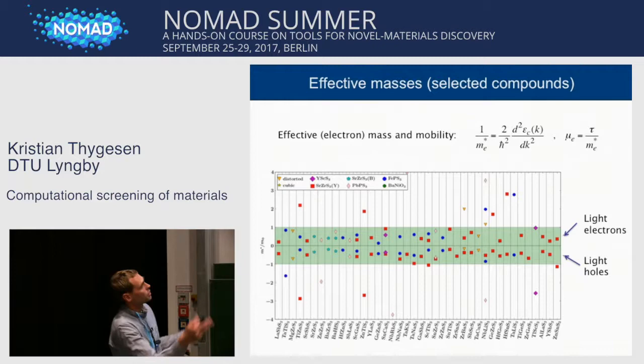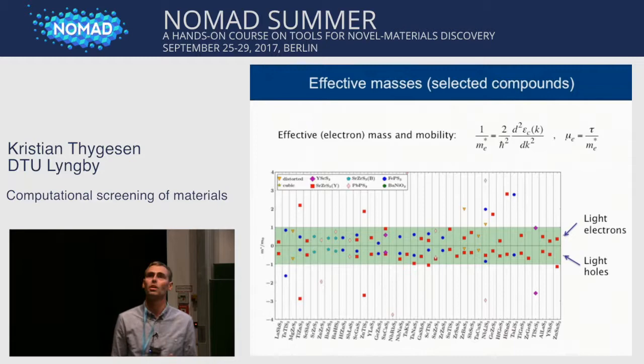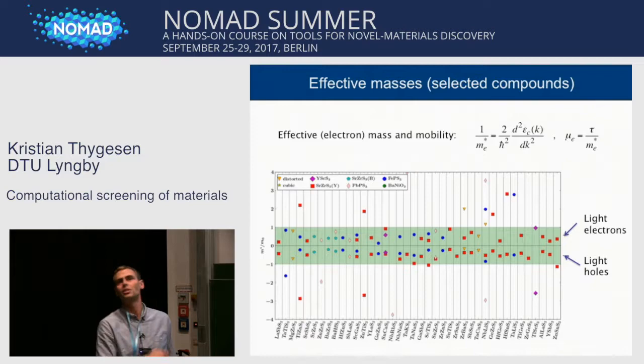So you can see there is another parameter up here, which is the relaxation time of the material. This is a parameter that is very hard to calculate from first principles. It depends on how many impurities you have in the material. It depends on electron-phonon coupling and so on. So this is something we will have to assume is the same for all the materials. And then we will use the effective mass as a descriptor for how high the mobility is.